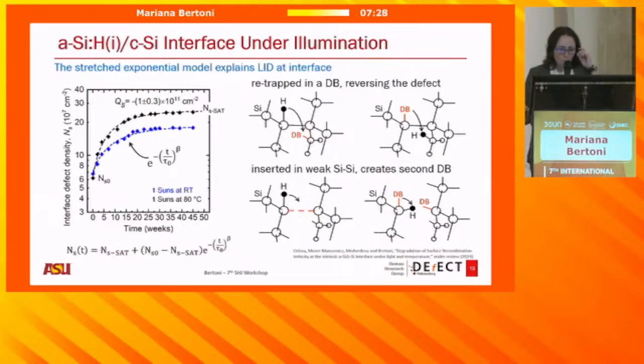So when you actually start looking at the stretch exponential behavior, here we have the light degradation at room temperature, and then you have an extra bump when you apply light. This is me trying to express all the molecular dynamics in sticks and balls. You have a dangling bond that retraps your hydrogen, and then your dangling bond moves back, and then you create another dangling bond. So your interface becomes extremely sensitive to light. And many of you have seen several papers from a couple of decades ago proposing similar behaviors.